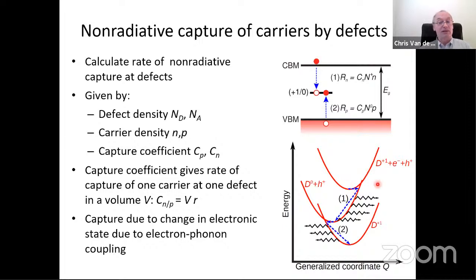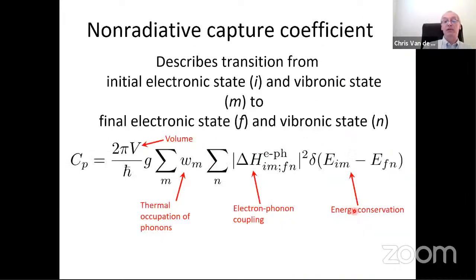But of course, nature is not classical, nature is quantum mechanical, and that means that simply using these classical barriers is actually not very accurate, but we can calculate the actual rates with which these transitions happen really based on quantum mechanical principles. So I'll just flash the equation for the rate that we use. You will recognize that this rate is basically an expression based on Fermi's golden rule. You see a matrix element squared, and you see, well, maybe not directly, but there is a density of states there, which comes about because of energy conservation.